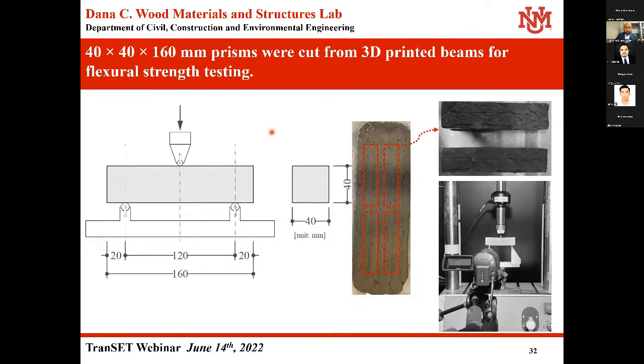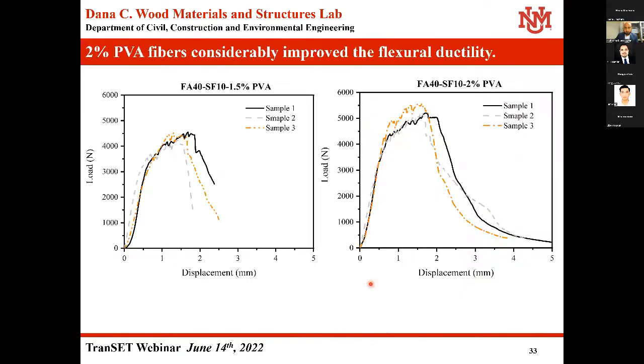To measure the flexural strength, we printed a beam and extracted 40 by 40 by 160 mm prisms from that beam to check the flexural strength of the printed specimen. And as you can see, we also compared the effect of fiber content for both 1.5% and 2% of fiber. There was a considerable improvement in terms of flexural ductility when we add 2% of the polyvinyl alcohol fiber in the mix.